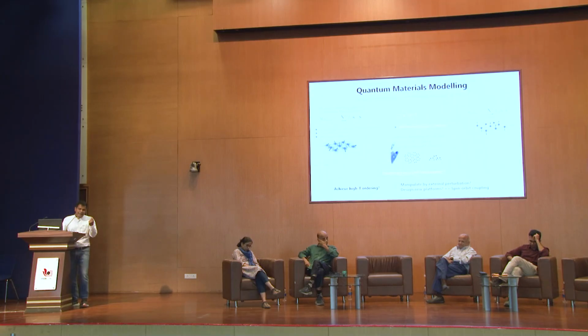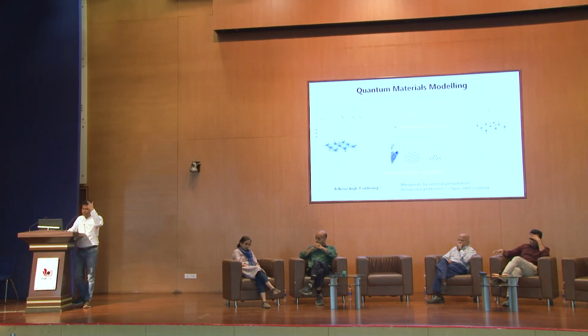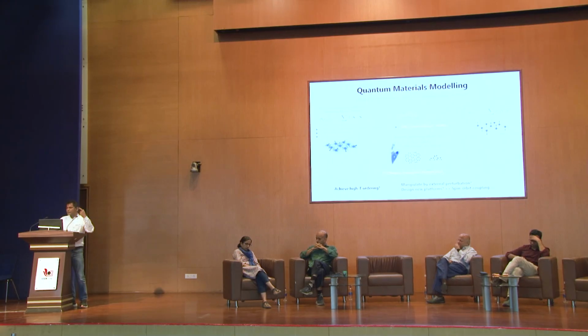Now, as I said, they have a cryogenic temperature because your anisotropy is small, and anisotropy comes from the spin orbit coupling. So a natural design principle would be, if you can crank up spin orbit coupling, then probably you can also crank up the TC. And that is one of the approaches we are taking at the moment: find materials, or take materials, where spin orbit coupling is higher.